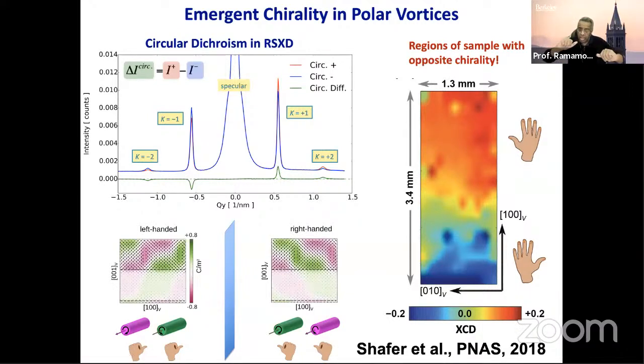Now, there are only two known mechanisms by which you can have circular dichroism. One of them is ferromagnetism, which of course our material is not a ferromagnet. But the other way is if the material is chiral. Okay, what is chirality? Here is a quick cartoon at the bottom. You can see that this is my right rotating vortex and this is my left rotating vortex. And it turns out that these vortices have an axial component as well going through the core of the vortex. And so if you now calculate the so-called chirality, this vortex array would be a right-handed vortex. Similarly, if I just simply flipped the directions of these, I could create left-handed vortices. Okay, so although the vortices are rotating left and right, they all could be right-handed or left-handed.